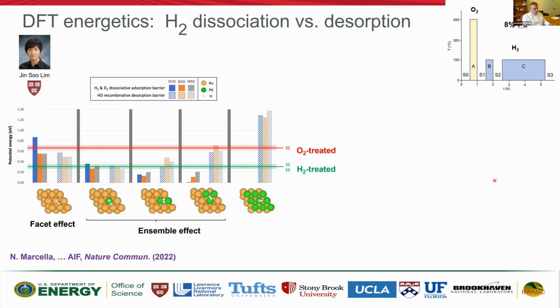And I'm moving now to the theoretical part. So after this information is known to us, what to do with that? What we are ready now to consider is that theory does not start with some kind of subjective model that is not informed by anything. And even if it was informed by some surface science experiments, it's still far from the reality of real operando catalysts. But now it is informed by real operando catalysis studies. And what we know from them, from Zane's analysis particularly, is that the oxygen treatment and hydrogen treatment correspond to different structural distributions of palladium. We also know from activity measurements that activation energy of about, in this case in electron volts, about 0.65 or 0.7 electron volts under oxygen treatment regime, and about 0.35 under hydrogen, can be modeled theoretically.